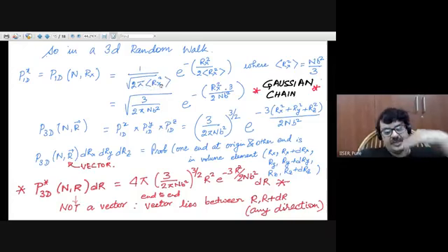So there was x square, now it is Rx square, net displacement in the x direction with a certain value. So this is a Gaussian function, right? And Rx square can be replaced by N b square by 3, so you have a 3 coming here, right?